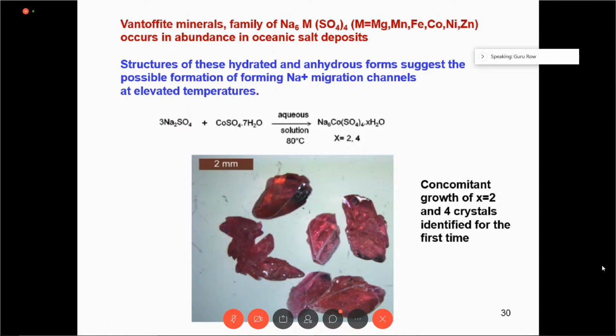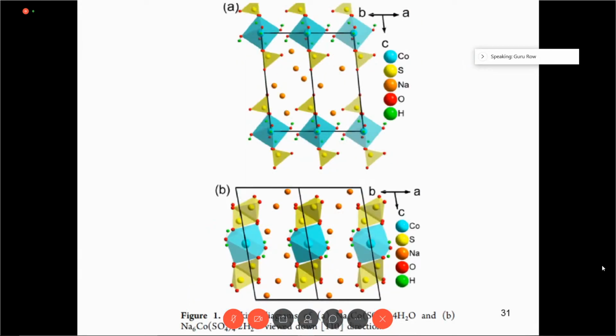And as a consequence, it is essential that we separate the X equals 2 from the X equals 4 crystals. This is a famous, very difficult job, and it was done over the X-ray diffractometer. We had to take each and every crystal and measure the crystal structure, or in fact, at least get to the cell dimension, which told us whether it is a 2H2O or a 4H2O.